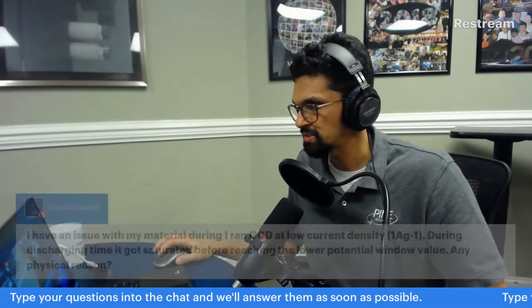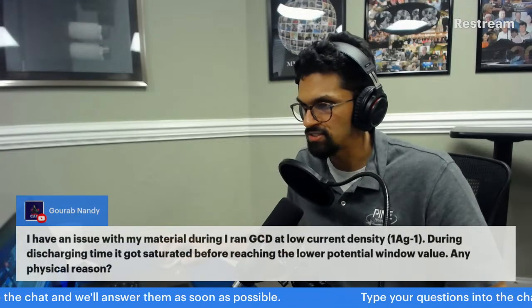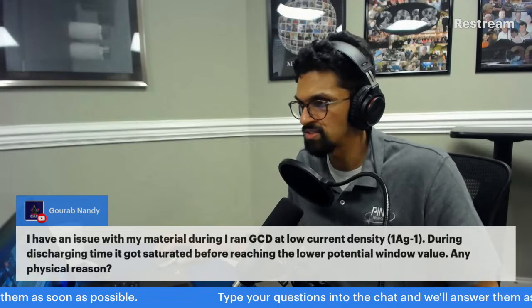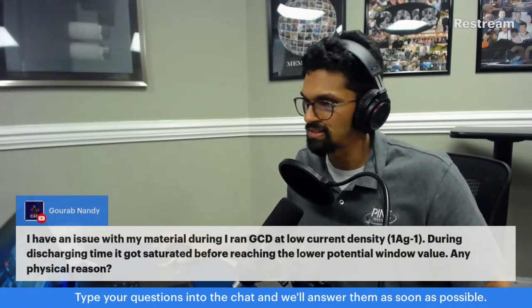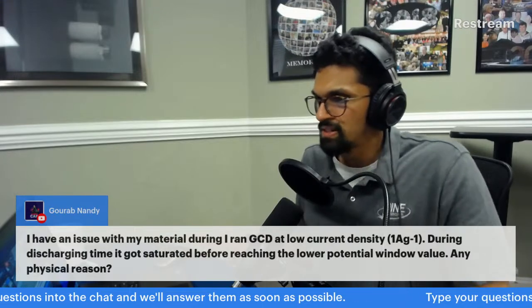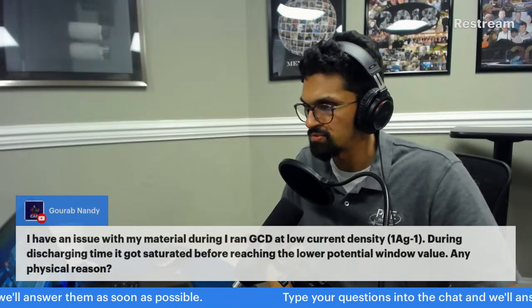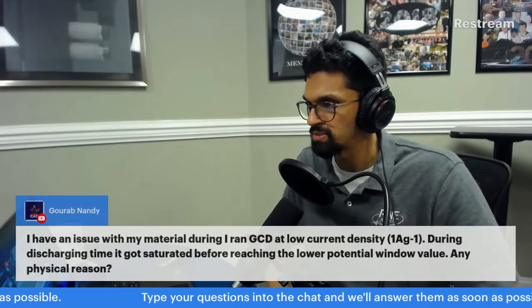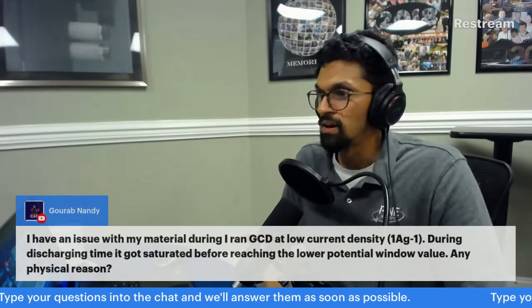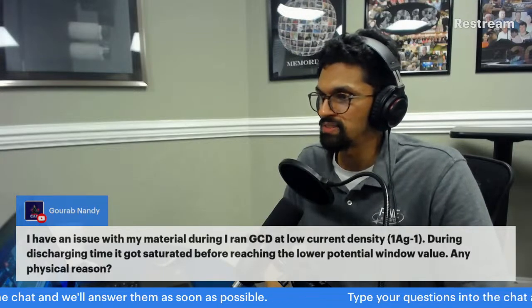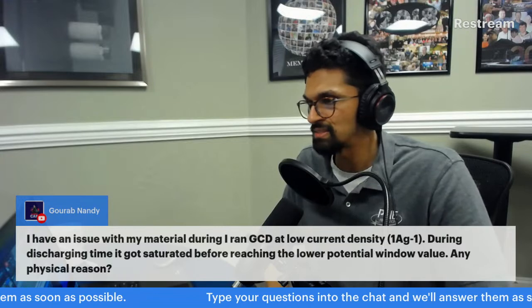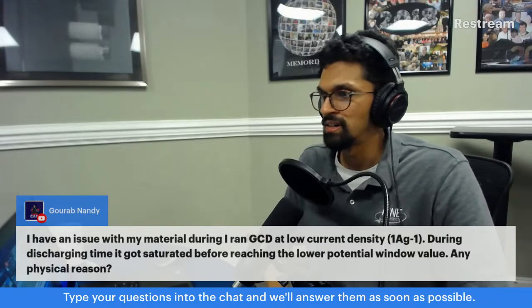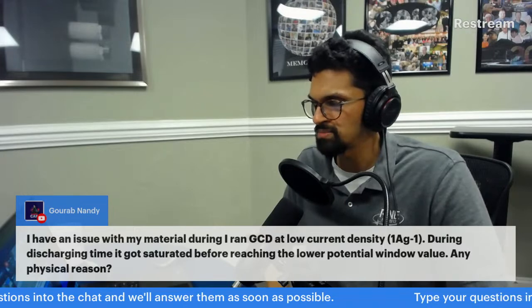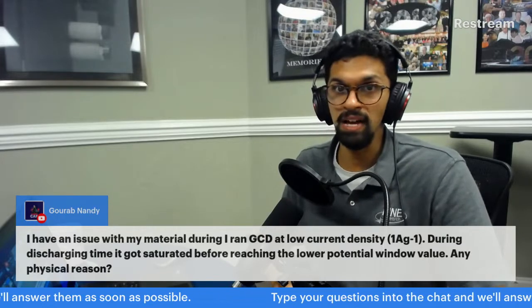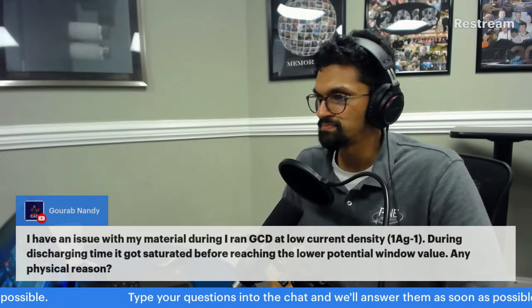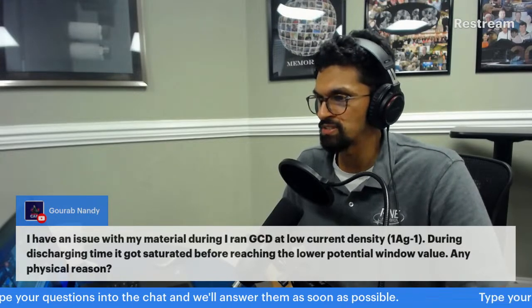I think actually before I get to the album, let me see. I have an issue with my material during galvanostatic discharge. At a low current density, 1 amp per gram, during my discharge time, I got saturated before reaching the lower potential window value. Any physical reason? Oh, so if you've been running galvanostatic charge discharge, even running low current density, which I don't know, 1 amp per gram, I don't know, that sounds high, but I'm not a battery person. During discharging time, I got saturated before reaching the lower potential. Any physical reason?